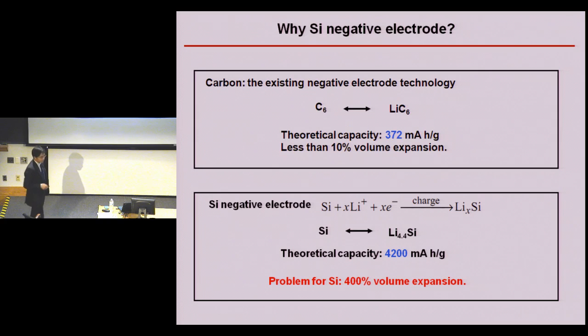So one exciting material is actually silicon. From this reaction, you can see lithium will be able to insert into silicon and form a lithium-silicon alloy, and one silicon can actually take up to 4.4 lithiums. And from this simple reaction, we can calculate that the theoretical capacity for silicon is about 4,200 milliamp-hour per gram, which is 10 times higher than the current negative electrode based on carbon.